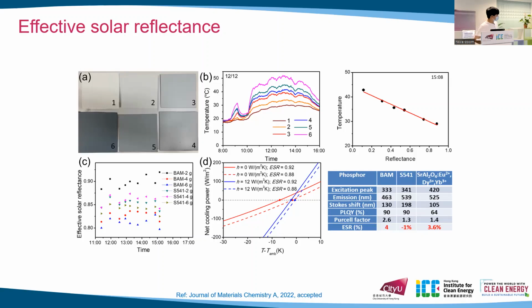As a result, we find that only the coating with BAM can achieve a higher solar reflectance than the white one. The white coating has a solar reflectance of 88%, but after adding the BAM, it achieves 92%. And we make a comparison among all the phosphors we use for these two works. BAM and S541 are used for this work, and the third one is used for our previous work. We can see that the emission peak of BAM matches best with the TiO2 nanoparticles' Mie scattering, and it also has a high PLQY and a small Stokes shift, so it has a higher Purcell factor, and it can improve the solar reflectance the most, up to 4%.